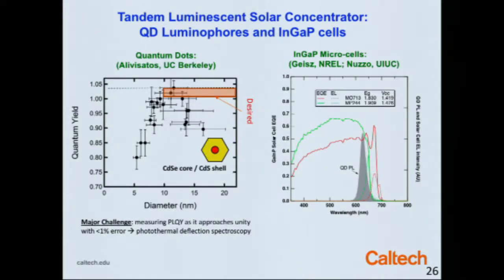More recently, we've been working closely with my good friend Paul Alivisatos in Berkeley, one of the pioneers in quantum dot technology. We can now emulate the process developed in his lab to make quantum dots that are indistinguishable, in terms of measurement error, from 100% luminescence. It's less than 100%—we just don't have, at the moment, accurate enough measurement techniques. In fact, one of the things we're working hardest on right now is new, better techniques for luminescence measurement. But anyway, we know now that the luminescence quantum yield, the radiative efficiency, can be greater than 99%.